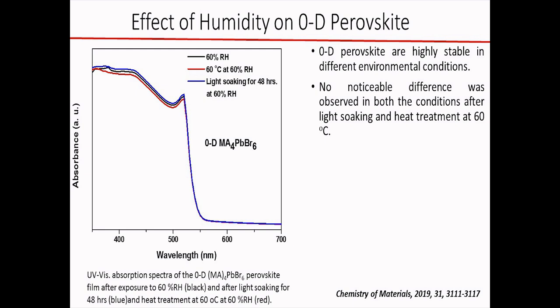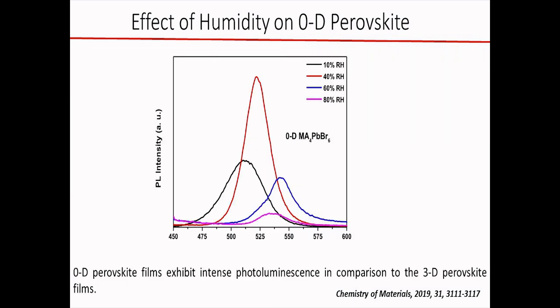We also kept it under light because there is also some degradation that has been observed in previous literature for 3-dimensional perovskite. But in the case of the 0-dimensional perovskite, we didn't observe any kind of degradation in the light either. This material has got some interesting properties with respect to photoluminescence.